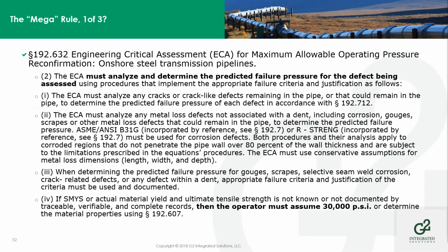You must analyze and determine the predicted failure pressures for the defect. And you must assume, if SMYS or actual material yield and ultimate tensile strength is not known or not documented, then the operator must assume 30,000 or determine the material properties following 607. So it's either one or the other.